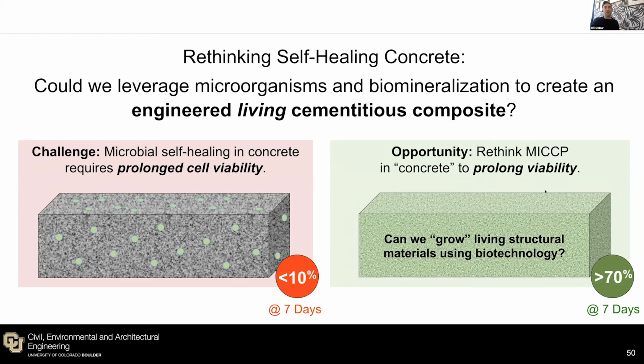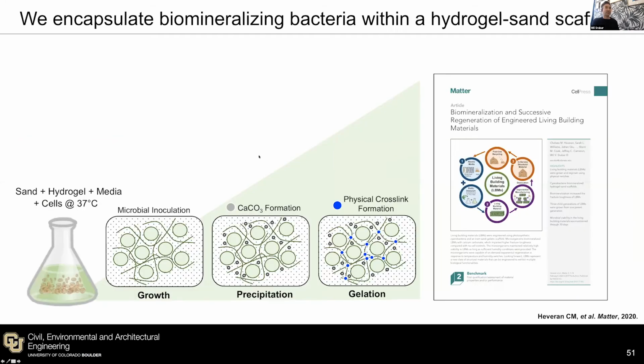So our goal was to grow a living structural material using this biotechnology and to keep it alive, have more than 70% of the initial inoculum survive at 7 days and longer. And this is what we came up with. So we took biomineralizing bacteria and we encapsulated it within a sand and hydrogel scaffold.